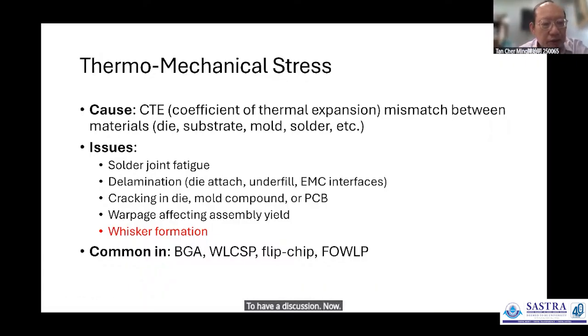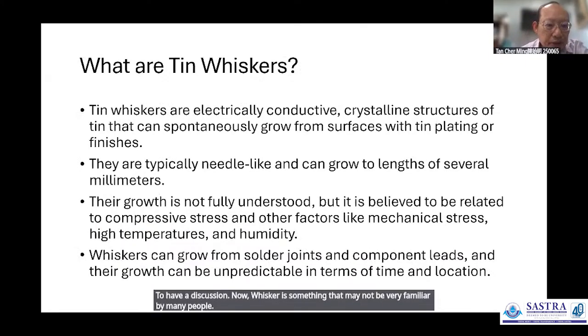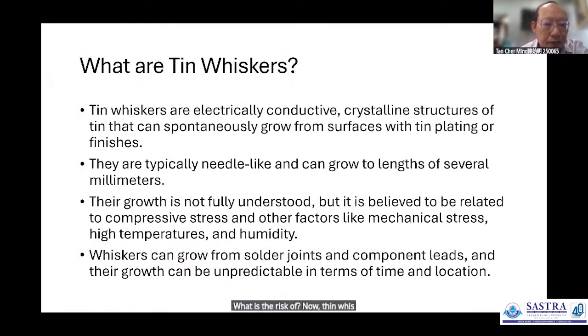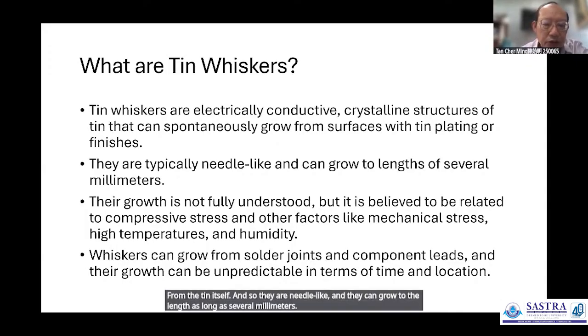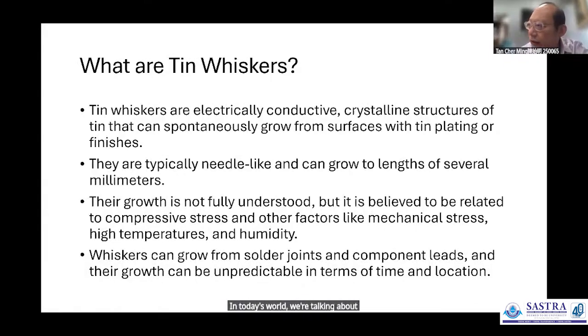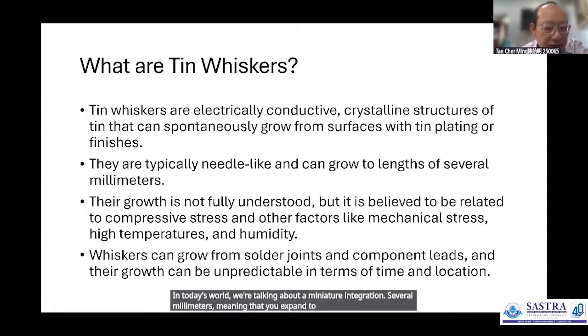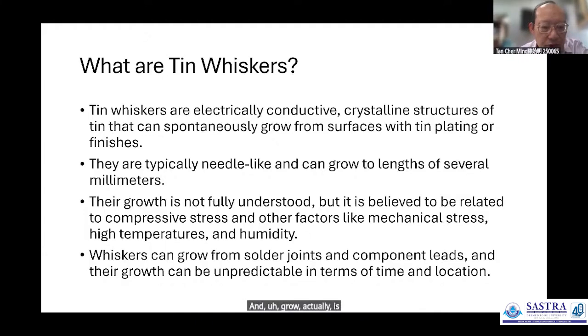Now, whisker is something that may not be very familiar to many people. What is a whisker? Tin whiskers are electrically conductive. They are really a crystal of tin that is grown from the surface of the tin itself. They are needle-like and they can grow to a length as long as several millimeters. In today's world, we are talking about miniaturization and integration. Several millimeters means that it can span several dies, several contacts. And the growth is actually not fully understood.